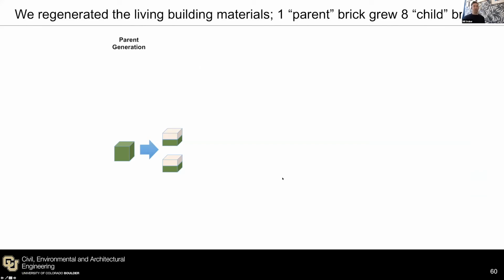And so one of the last things I'll discuss is that we actually regenerated the living building material and demonstrated in our publication that one parent brick we can keep alive and it can grow up to 8 child bricks without the addition of new bacteria. So what we did is we made one living building material, what we call the parent generation. We split that into 2. So we took 2 halves and we added more abiotics. So not new cells, but we added more sand and we added some more media.